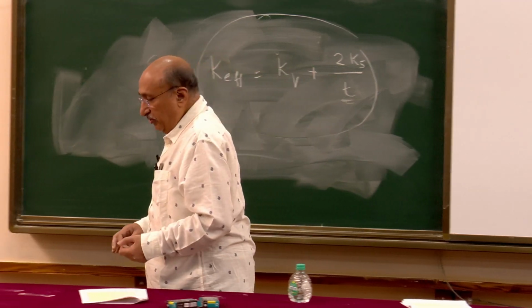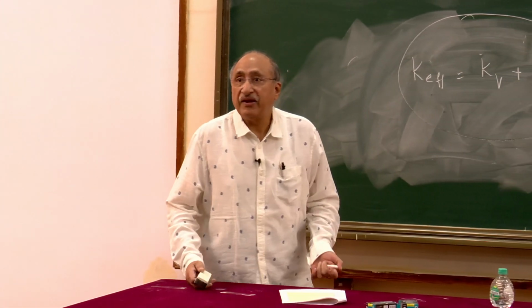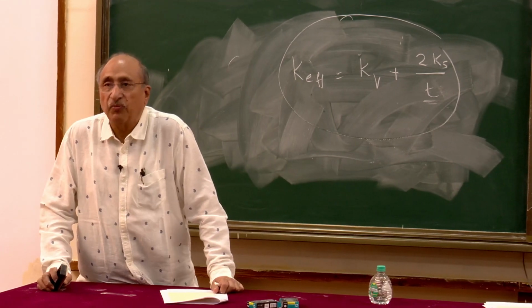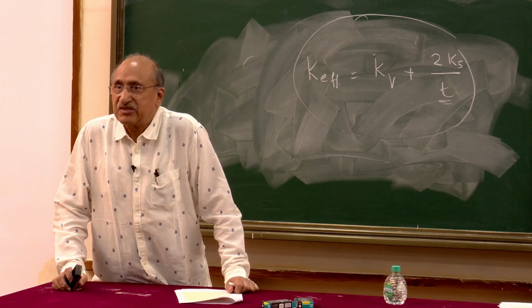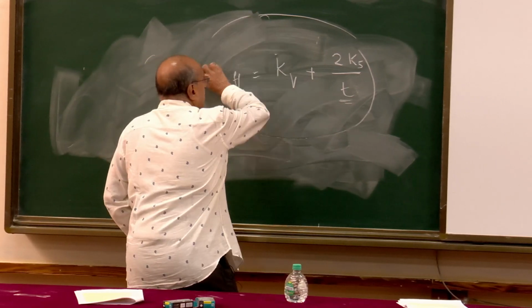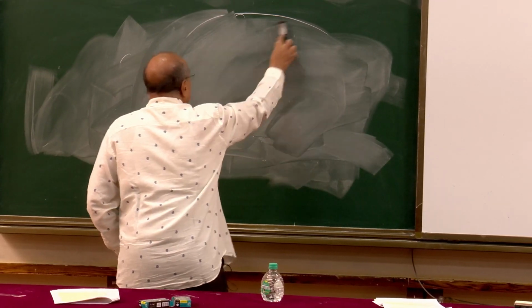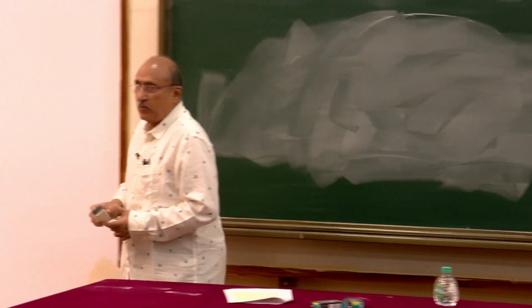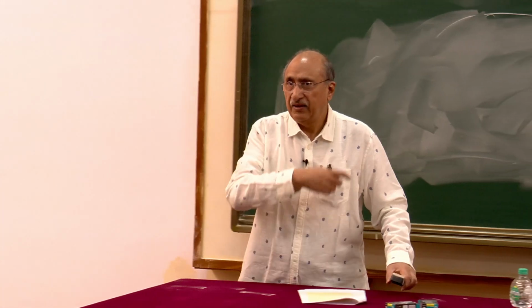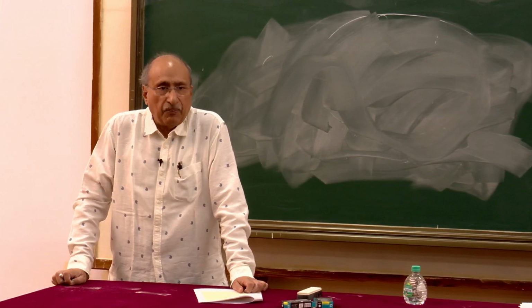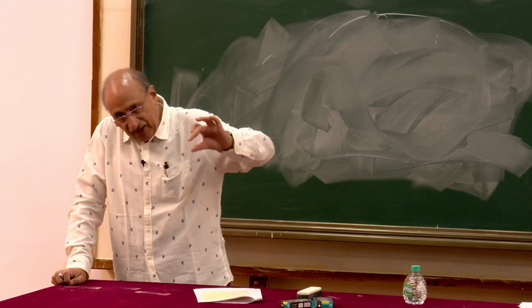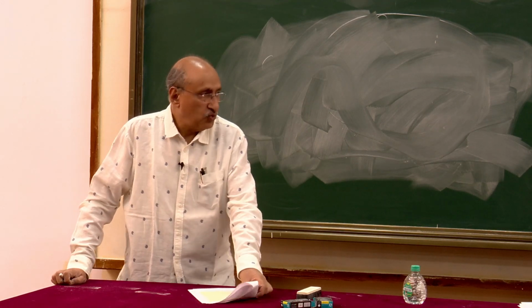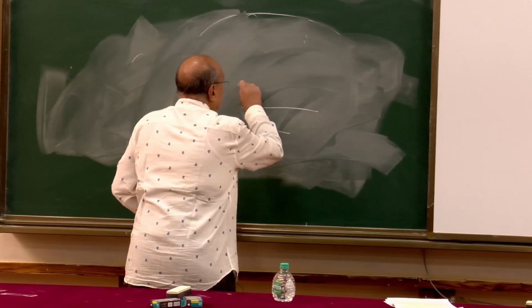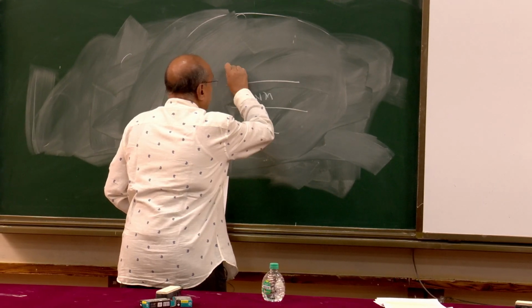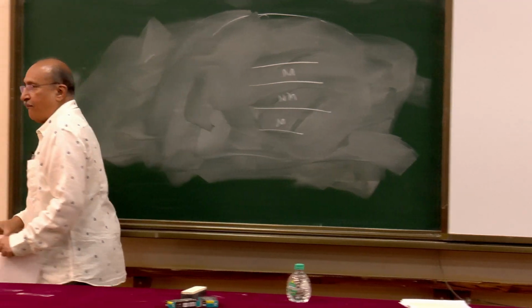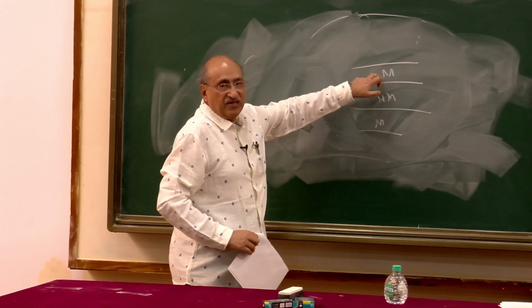The third thing I will talk about is, of course, the famous experiment by Fert and group, and also by Grunberg, I must not forget, about giant magnetoresistance. It depends on how the magnetic films in a multilayer couple to each other. If I have time in my next talk, I will give you some FMR data on the coupling of two layers with a non-magnetic layer in between. So you have a film here which is magnetic, then non-magnetic, and then magnetic. Whether there could be coupling between this and this.